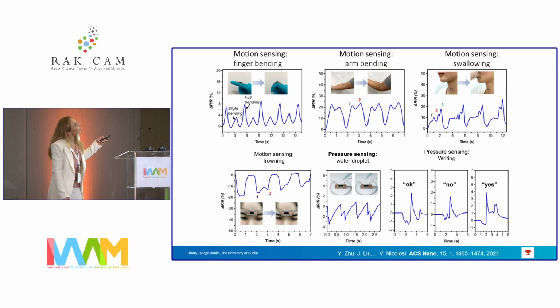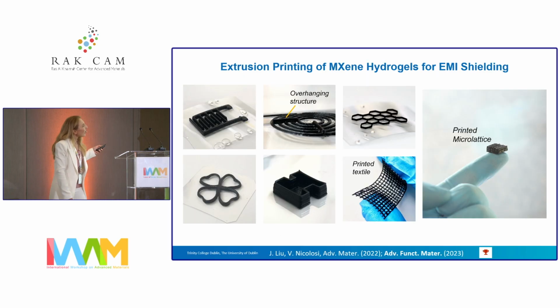So in this case, you can also detect the arm bending, you can detect the different phases of swallowing, if you have it here in the throat, forearm, frowning of the forehead, pressure sensing for a water droplet being dropped on the film, and you can even use it to sense writing. Very small words, but again, it's good as a proof of concept. And of course, they are very, very nicely printable inks by extrusion printing.